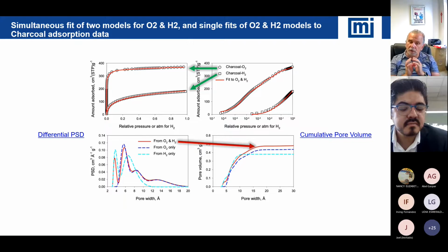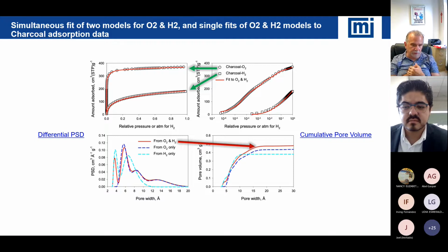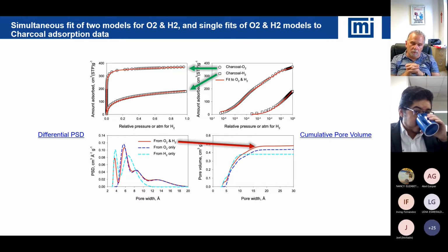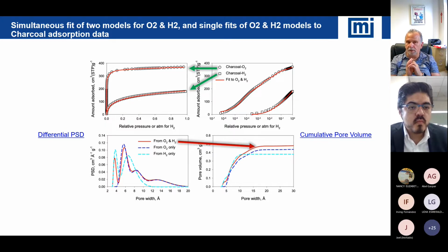So yes, you can obtain very good pore size distribution data on both. As the particle gets bigger and you get to these practical sizes you're talking about, what you want to be more careful about is how long it takes to make the measurement, and be a little more cautious about the timing, since it may take longer for equilibration for larger sizes like extrudates or pellets. The additional time is because it's more difficult to remove the heat. If I've got a fine powder in contact with a very cold surface, I can easily remove the heat during adsorption, and the heat tends to really slow down adsorption.